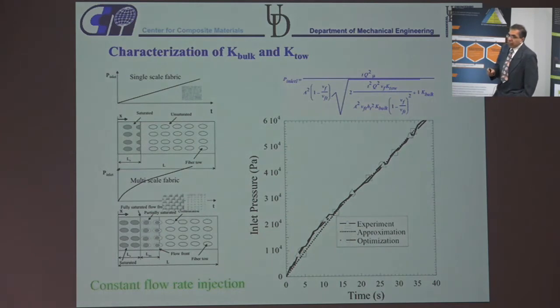So of course the other thing is, how do I find this second permeability? So we came up with an analytical solution for a dual scale porous media. So what happens is, when you have a single scale porous media where the tows and the resin along the tows are filling at the same rate, the pressure, if you inject at a constant flow rate, increases linearly. Okay, that will tell you it's a single scale porous media when you do this experiment.